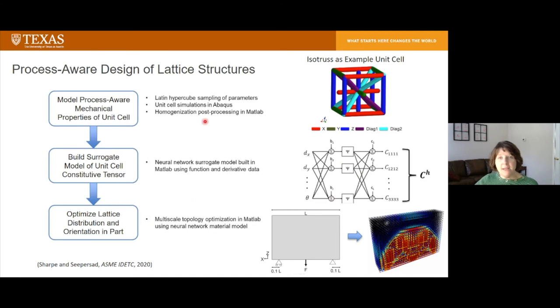So what we've done is we've taken that information and input it into a design process. So here we've got an example isotruss unit cell for a lattice structure. You'll see it has vertical, horizontal, and diagonal struts. So what we do is we model the properties of those struts based on what we've seen in our experiments. And so from that, using what we call a geometric projection method for doing the analysis in Abaqus finite element, then we get all the properties of these unit cells as a function of the particular diameters of the struts and the orientation of the cell.